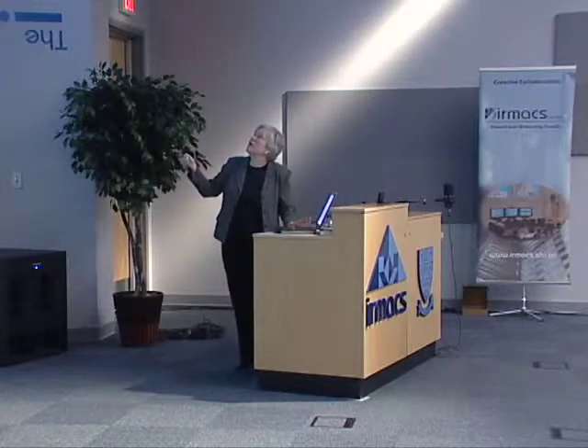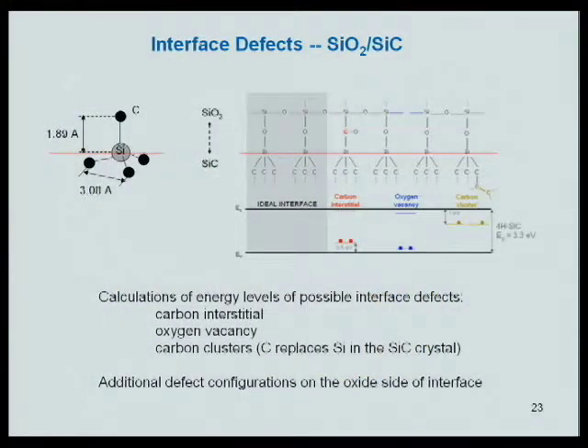And so what might these defects be at the interface? The red line here, the interface, represents the surface of the silicon carbide. Here in 3D, we have silicon atoms on the surface that are bonded to three carbon atoms just below the surface. And this silicon is going to bond with oxygen and start to form the oxide layer on top. So here we have oxygen bonded to silicon, and this is what the perfect interface might look like. But here we have what might be a defect, and this is called the carbon interstitial, where there's an extra carbon here.